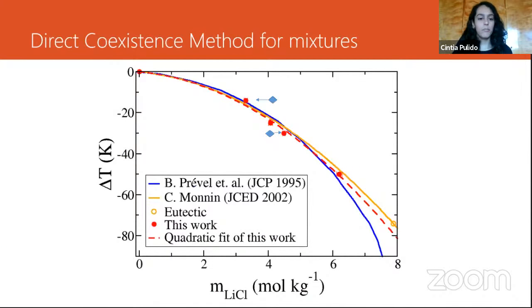So here we have an example in the phase diagram of what we did. The blue marks indicate where we simulated a system. This system was the same one, and we ran it at 3 different temperatures. We can see that when we started at a temperature that is really similar to the coexistence one, the system did not move. The concentration of the solution was the same at the end. And when we started at a temperature above coexistence, part of the ice melted. So now we have a smaller concentration in the mark above, and in the one below,